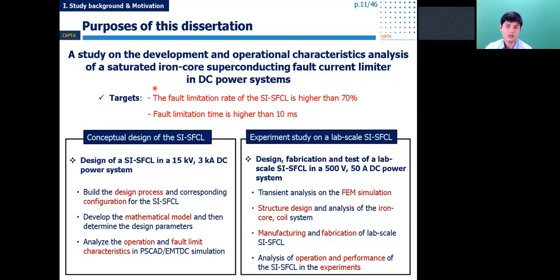In this dissertation, the author developed a conceptual design of the SI-SFCL for the distribution VSC-based MVDC power system, and then a lab-scale prototype SI-SFCL was designed, fabricated, and tested to confirm the effectiveness of the SI-SFCL through experiment. The SI-SFCL was designed with a targeted fault limitation rate of higher than 70% and a fault limitation time of higher than 10 milliseconds.